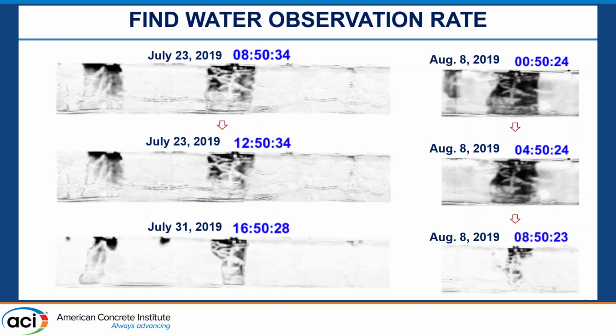The leaking area from the stadium was causing problems with the ASR underneath, and these problems were able to be quantified in terms of how much moisture. We could even predict when it rained there, because we were able to see the change in patterns just based on these images. So we could say, yeah, it started raining in the morning and it rained all day, or it stopped raining about this time because the structure dried to a certain point by the afternoon.